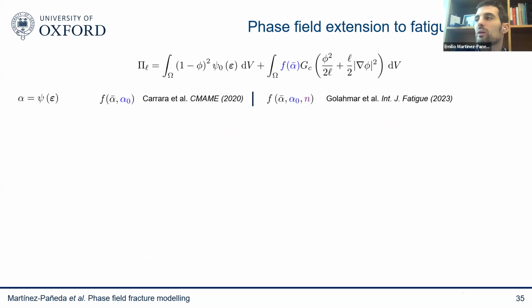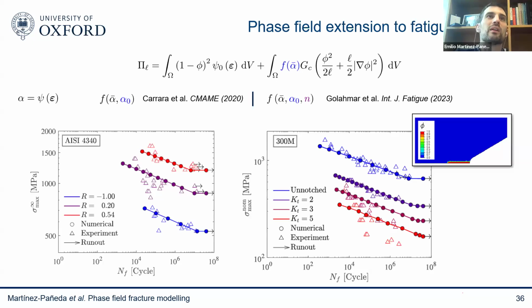One thing we did work in my group is that we realized that this model of Laura was very good. It was a very nice framework, but we weren't able to get quantitative agreement with experiments. So we extended the model to account for an extra parameter. And I don't have time to get into the details, but the paper's out there for anyone who's interested. The price to pay was to add an extra parameter. But the advantage is that we were able to predict quantitatively what we see in the experiments.